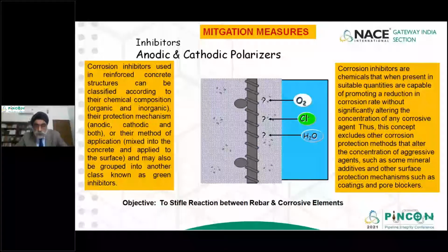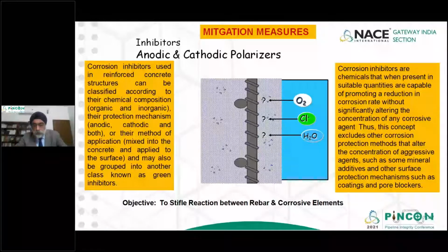Then for buried structures and also for above ground structures, another technology which is being used in case barrier coatings are not used is to use anodic and cathodic polarizers. Now these are basically corrosion inhibitors which ensure that the passivity of the steel is maintained, and even if oxygen, chloride, moisture enters the concrete cover, it would not cause corrosion on the rebars. Now this has a limited duration, can protect the rebars for 10-15 years, not a long-term solution, but this is also used on many structures which are being rehabilitated. So a consultant has to decide which anodic and cathodic polarizers they want to use. But as I said, the life is limited.